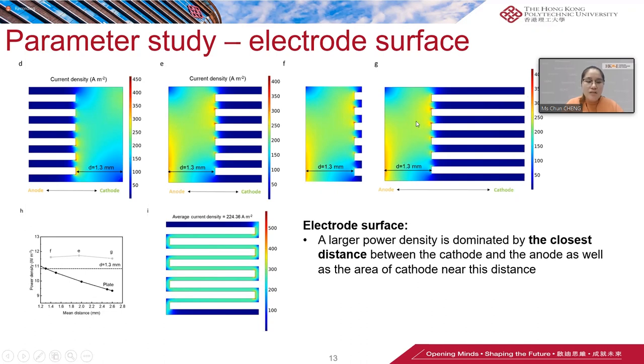to G, from which the high current density occurs at the cathode surface closest to the heat source and diminishes very quickly at the channel depth exceeding 1 millimeter due to the low mass transfer. These findings allow the inference that from the perspective of electrode design, a larger power density is dominated by the closest distance between the anode and the cathode, as well as the area of cathode near the distance. So a rational design of